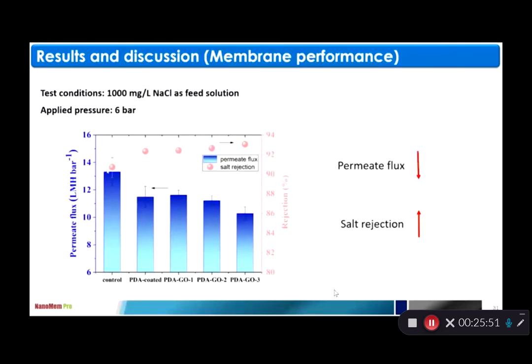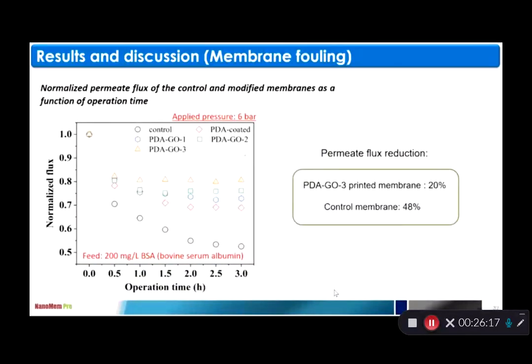And you can see the flux was initially 13 LMH per bar. And then when you have inkjet printed GO, the overall flux decreased a little bit. On the other hand, your salt rejection increased, which is the general trade-off between permeability and selectivity. Then, based on that, we also looked at different membrane fouling effects. So you can see the normalized flux in terms of different cycles of GO inkjet printing. So we use BSA, which is a very typical membrane foulant, and this is the control. It decreased almost 50% without any inkjet printed GO coating. However, when you have 3 times the GO coating, there is only a 20% reduction of the overall performance.